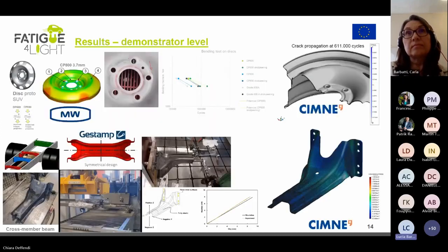Okay, and then we have two different demonstrators that were also analyzed in our project. First, the wheel. We wanted to analyze the performance of a wheel, mainly the disc of the wheel, which was a demonstrator proposed by one of our partners, Maxion Wheels. They designed a new stamping cycle for trying out different materials studied in the project and seeing their performance on this demonstrator. And what was interesting to observe here is that we saw that with the same stamping cycle, different materials have different performances after this forming cycle.